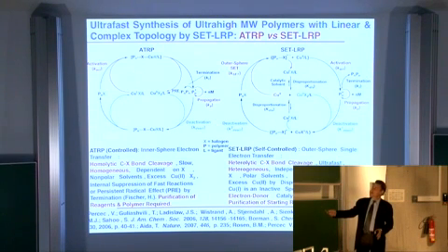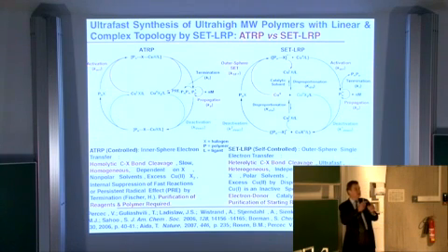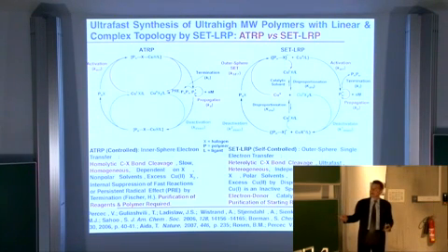As soon as you go from alkyl iodides to bromides and chlorides, the bond strength matters in the homolytic bond cleavage part of the reaction. The rate constant for this homolytic cleavage is bond-strength dependent. Therefore, you cannot activate any alkyl halide, and the reaction mixture needs to be very carefully purified.